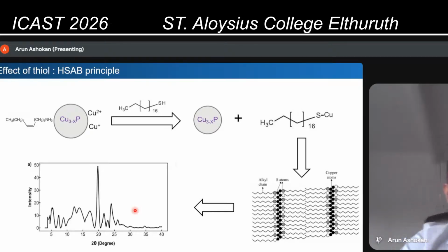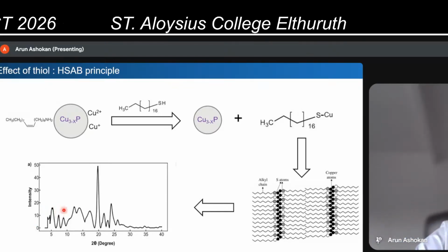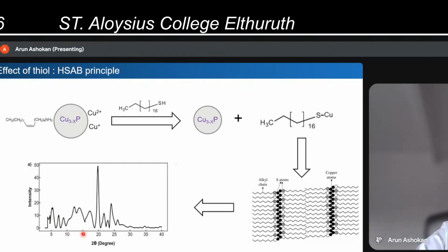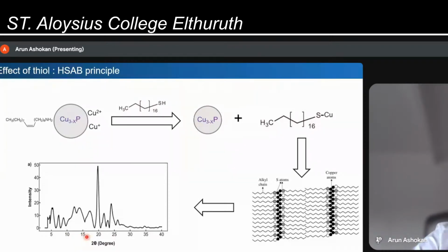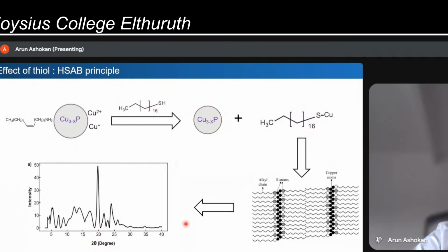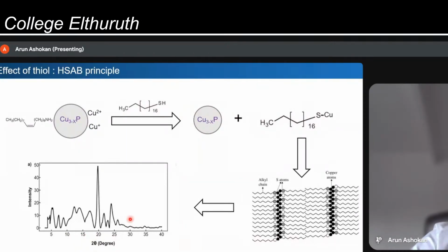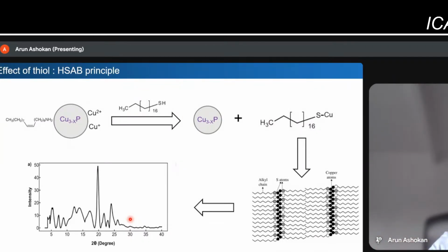They show scattering peaks at lower angles in the XRD. So we characterized that white precipitate using XRD as well. So they are copper thiolate. So basically, we are degrading the nanocrystals with thiol. So why do we do this?